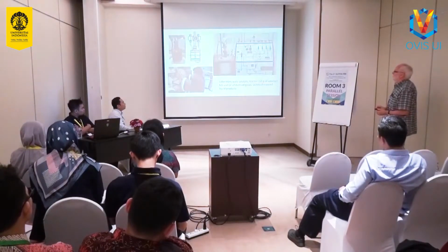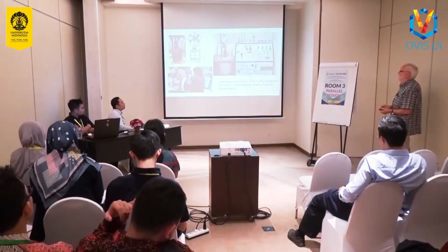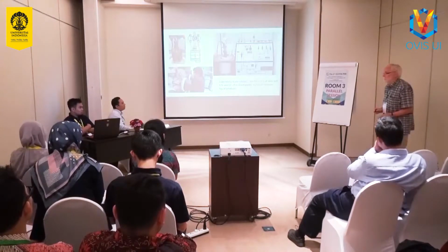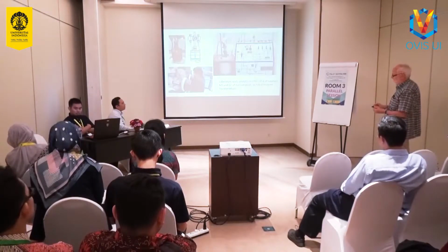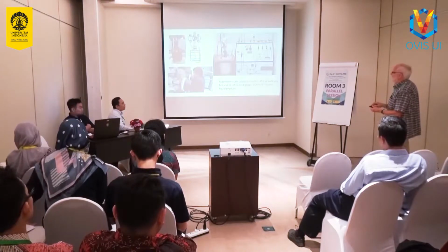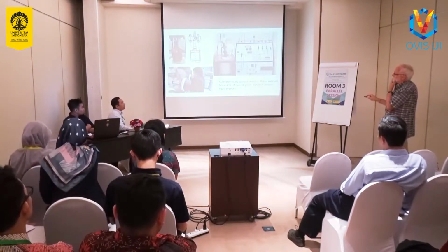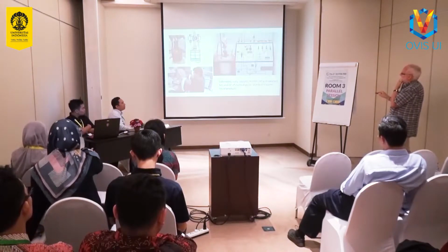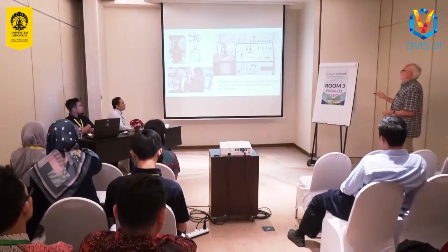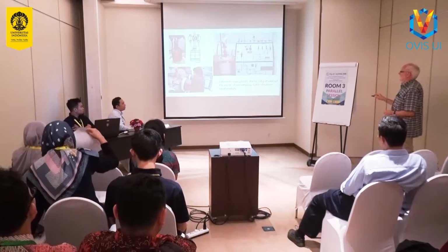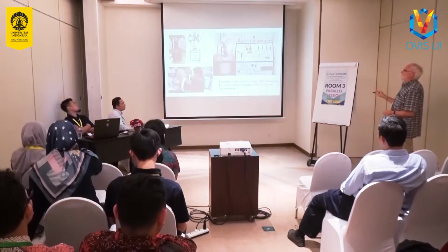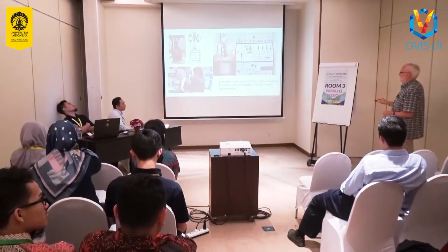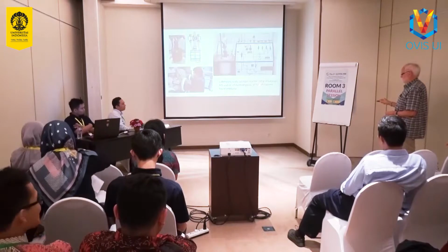Well, we use a reactor for preparing samples here, which contains about 15 grams of zeolite. We use a commercial zeolite, Johnson Matthey. It comes straight from the plant. It's not in any way adapted for academic use. And that goes into a reactor which looks like this, holds about 15 grams. That's mounted into a reactor system, which is a series of mass flow controllers for flowing different gases through the reactor in the furnace. And then we analyze the effluent by MS and GC. And we trap the heavy products for analysis afterwards by GCMS.